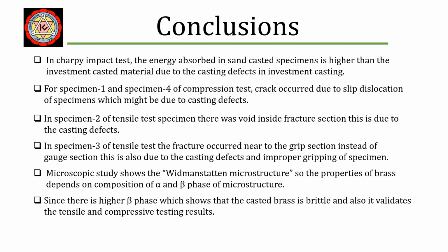Microscopic study shows the Widmanstätten microstructure. So the properties of brass depend on the composition of alpha and beta phase of the microstructure. Since there is higher beta phase, it shows that the casted brass is brittle, and it also validates the tensile and compressive results.